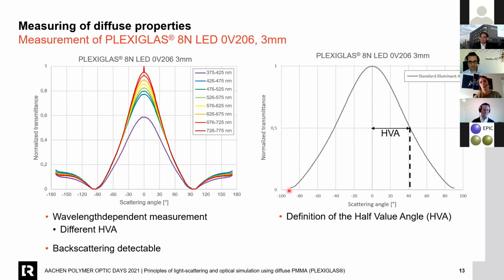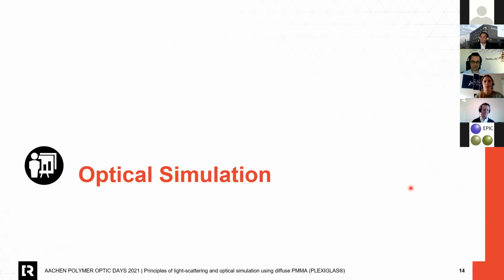On the right side, we have the diagram to define the half value angle. It's a scattering property of our material. This curve is the sum over all wavelengths weighted with the standard illuminant A and the luminosity function. And the half value angle is defined at half of the maximum transmittance. So for this product, we have a half value angle of about 40 degrees. So now remember these pictures because you will see them later again with our simulation results.